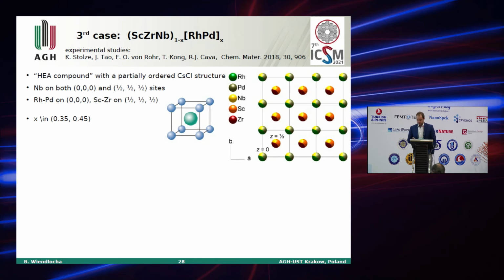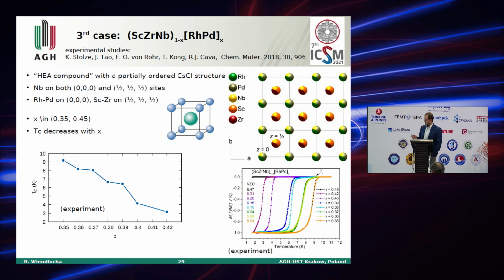And the last case which I would like to present to you today is the scandium, zirconium, niobium, rhodium, palladium high entropy compound. This time the system is a little different. It is called a high entropy compound because it's a partially ordered structure. So it has a cesium chloride structure, so it's like BCC but with 2 inequivalent atoms. And niobium occupies both of these positions, but we have a separation between these two sites because rhodium and palladium sit only on this 0, 0, 0, and scandium, zirconium only on this inside of the unit cell. And experimental work found that critical temperature is around 9 Kelvin for the optimal concentration, and it decreases when we increase the concentration of rhodium and palladium, so it decreases with X.